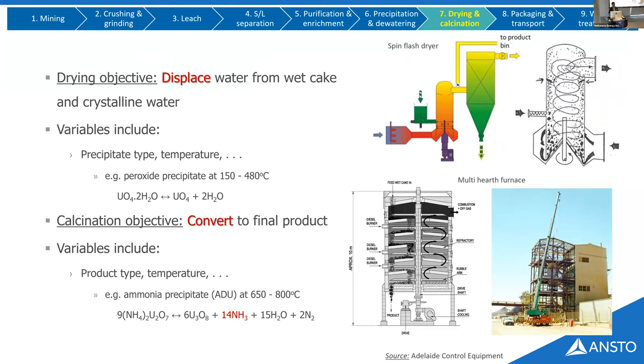Once you've got your precipitated material, you're looking at displacing the water and drying your product. You can do that in a spin flash dryer, for example. In this particular example, I've marked up the peroxide precipitate. You can look at about 150 to 480 degrees. It'll convert that, and in those cases, it'll also push off the crystalline water as well. And you can go even further and convert it to a final product, which is calcining.